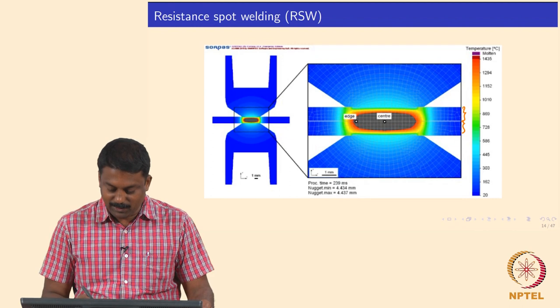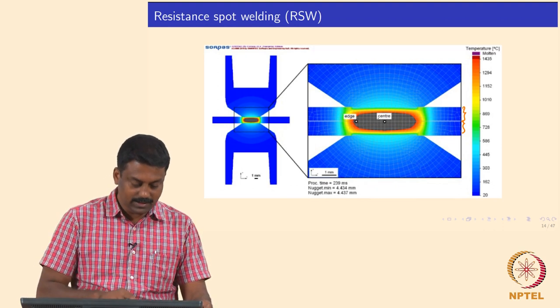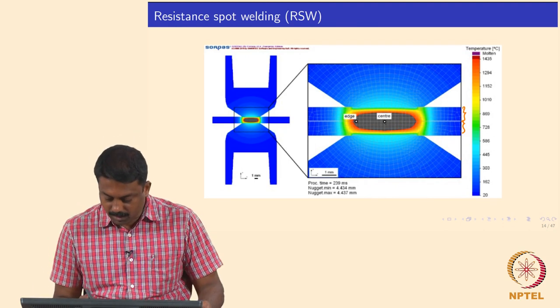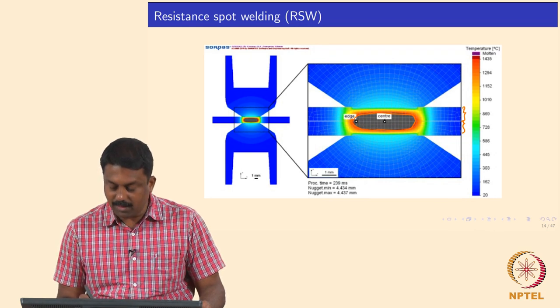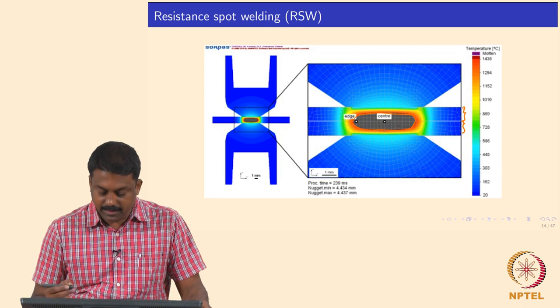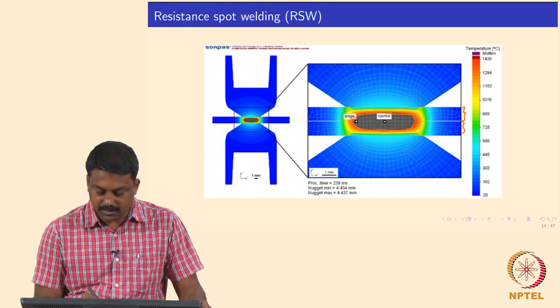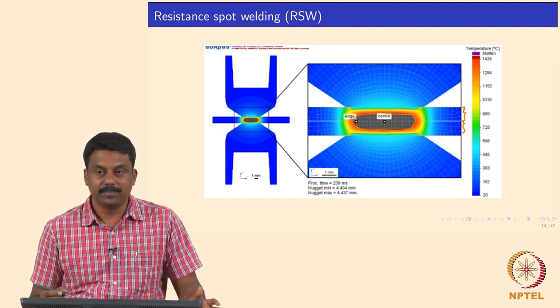If you look at the temperature distribution, this is the cross section of the electrode — the entire cross section — and this is the center. You form a fusion boundary, below which you have a heat affected zone and above which you have a weld centerline. The nugget formed is generally a particular shape. Splashing happens when the fusion boundary extends to the surface of the plate.